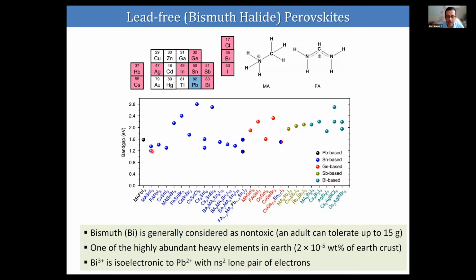But the problem associated with tin is that it can easily undergo oxidation from the Sn2+ state to the Sn4+ state, and that is not suitable for most applications. So that is the issue with tin. And with germanium, because of some issues, the band gap cannot be reduced much lower. Most of the germanium-based materials show a very high band gap like this.